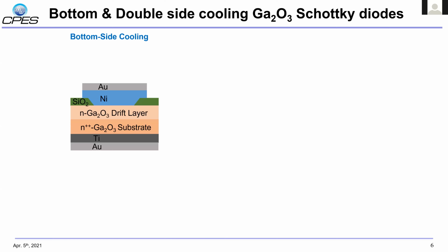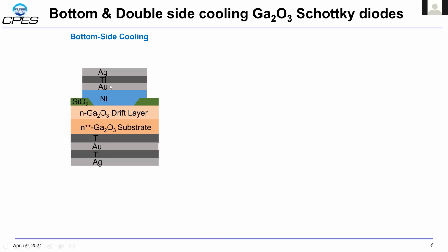Here's the packaging detail of the bottom and double side cooling gallium oxide Schottky barrier diode. First, for the bottom side cooling, here is a gallium oxide vertical Schottky barrier diode. There's a drift layer, a substrate, nickel and gold forms the Schottky contact, titanium gold forms the ohmic contact. Then we deposit 100 nanometer of titanium and 200 nanometer of silver for the silver sintering.